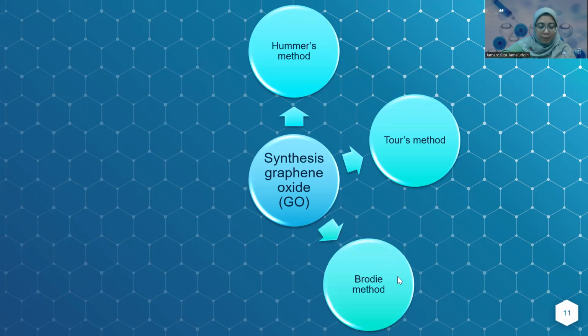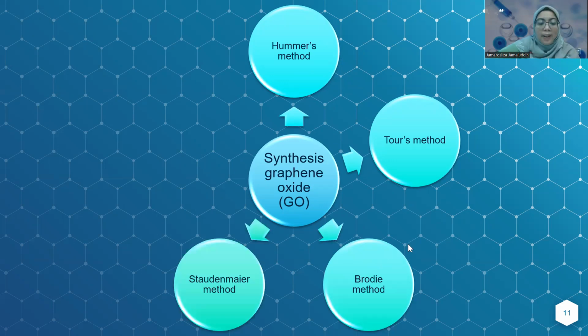The third one is the Brodie method. This Brodie method involves the use of a mixture of graphite and fuming nitric acid. This method is less hazardous compared to the Hummers method, but it requires long reaction times and yields low quality graphene oxide. And the fourth method, we have the Staudenmaier method. This method is similar to the Hummers method, but it uses a different oxidizing agent. This method has a low risk of explosion, but it's less effective at producing high quality graphene oxide.